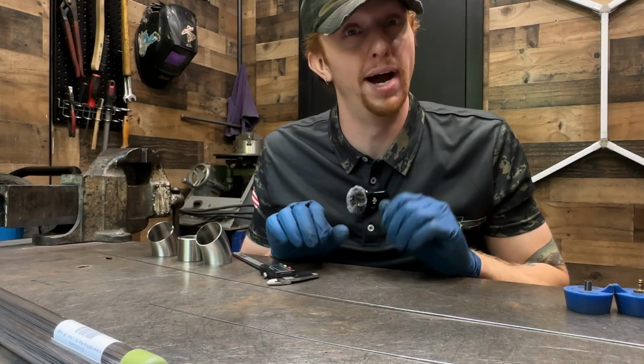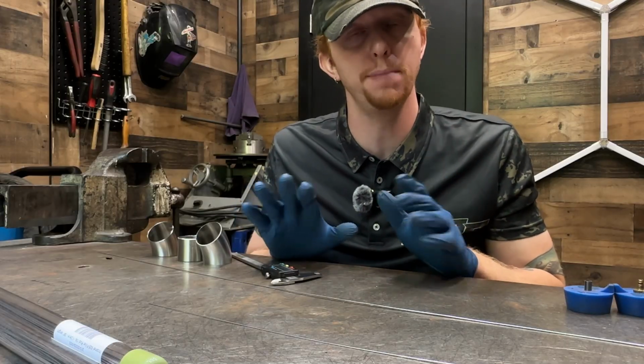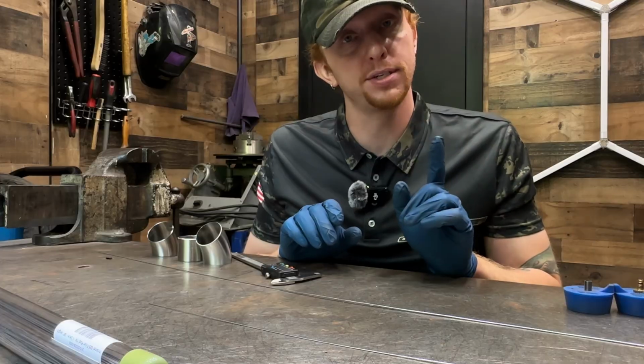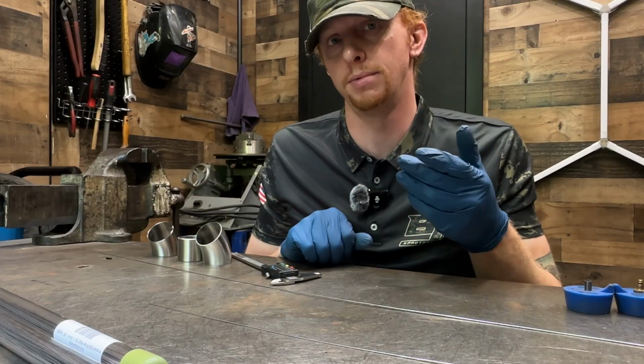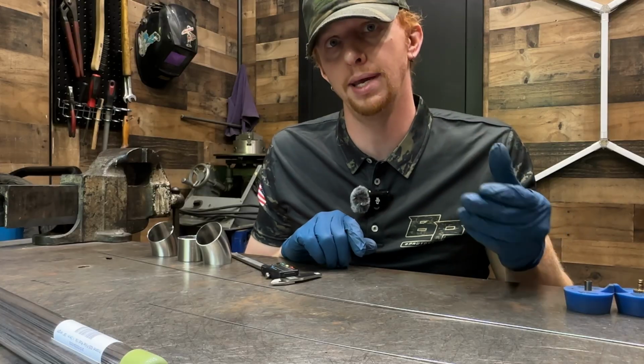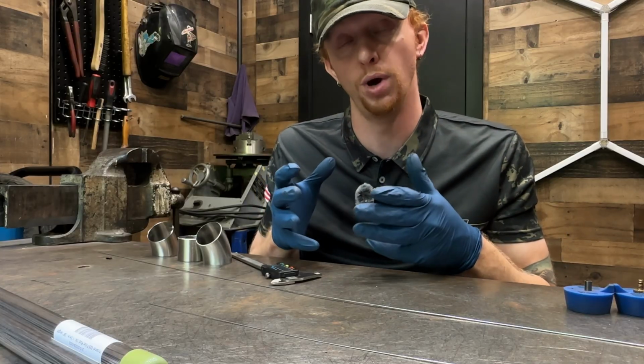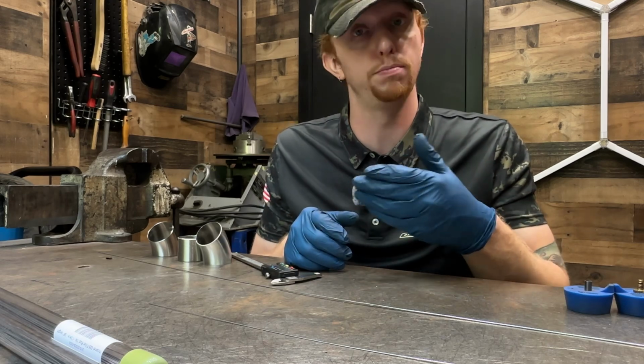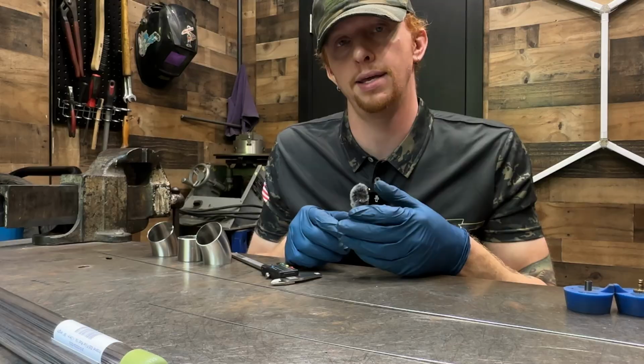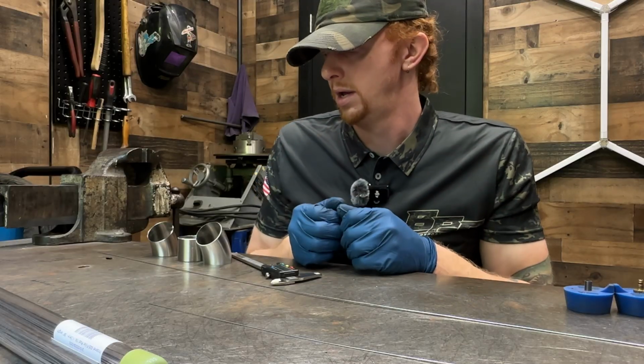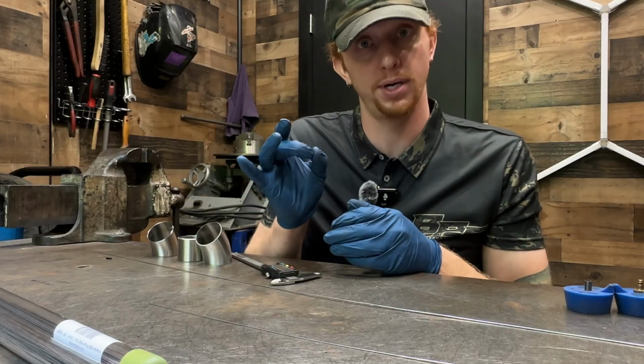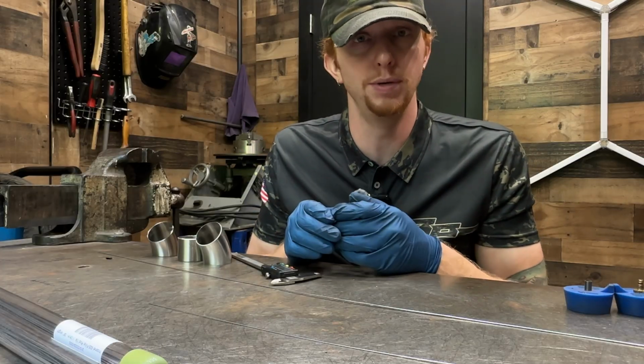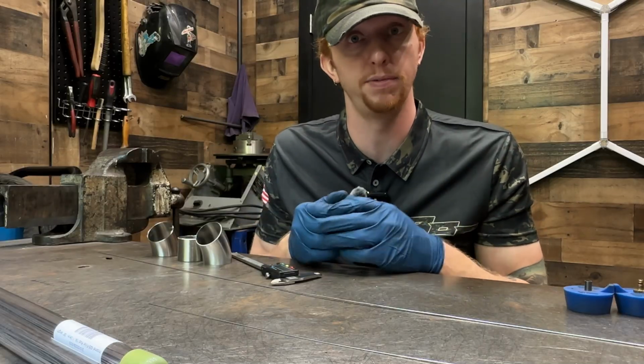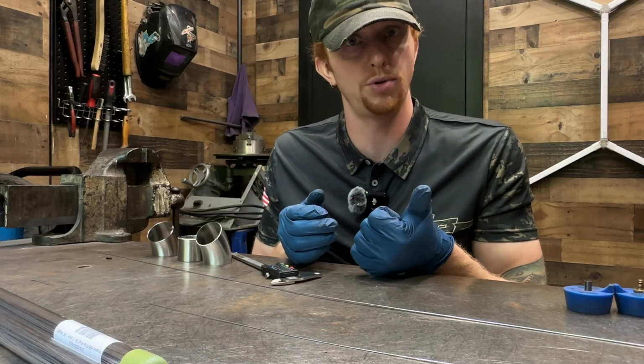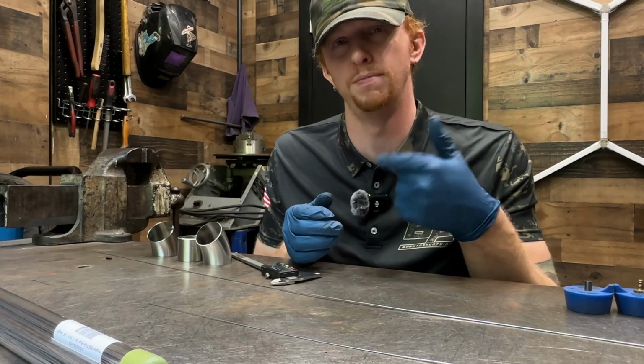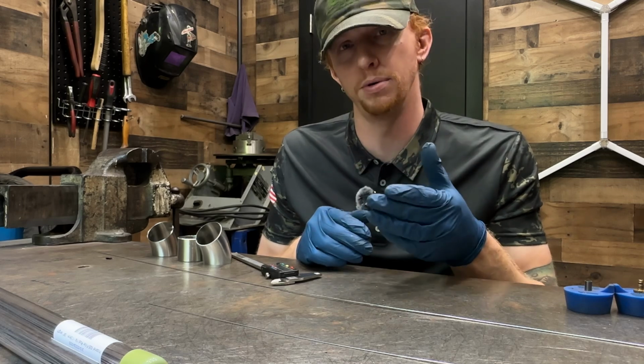Let's talk about welding nickel alloys now. There are a few things that you want to keep in mind as you're working with this material. The first of which is back purging. If you guys are not familiar with what back purging is, what you are doing in that process is filling the inside of the piece that you're welding with inert gas. In this case, it will be pure 100% argon. The reason for that is to shield the inside of the piece. Just like you shield the outside of it with a cup or a gas nozzle, the inside of the piece also needs to be shielded. Otherwise, it will pull in contaminants from the atmosphere and result in a weld that is not as strong as one that is back purged. And it will also result in a bunch of nastiness on the inside of the piece. I'll show both of those here in a little bit.